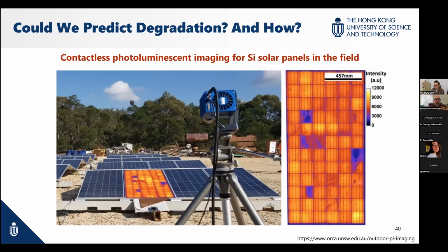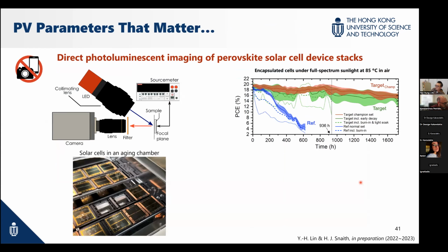We also look into a different way to characterize perovskite solar cells. One thing that is quite commonly used in the silicon industry is either electroluminescence or photoluminescence. Of course, with photoluminescence we don't need to operate the cell directly; we can observe the cells using a photoluminescence camera. So we had this kind of setup to examine those aged cells. Basically, we have a strong light emitting diode, then we have a camera with a filter, and then we are able to measure the photoluminescence intensity.